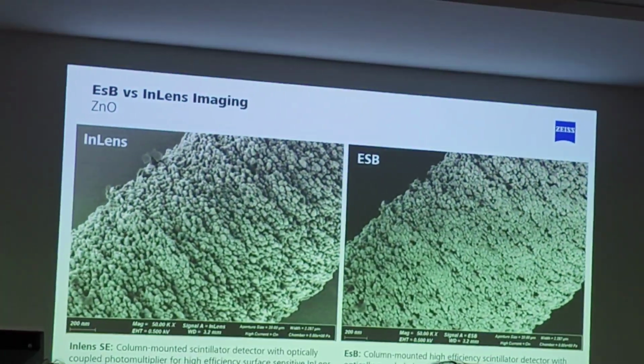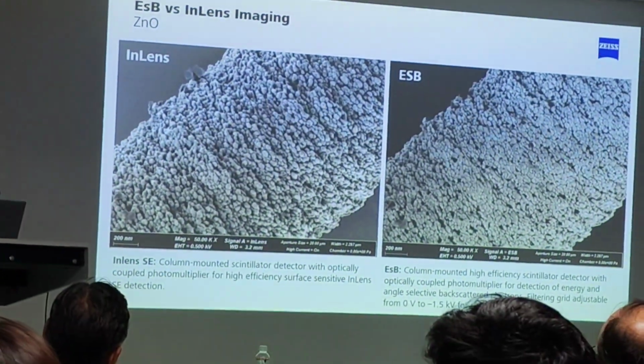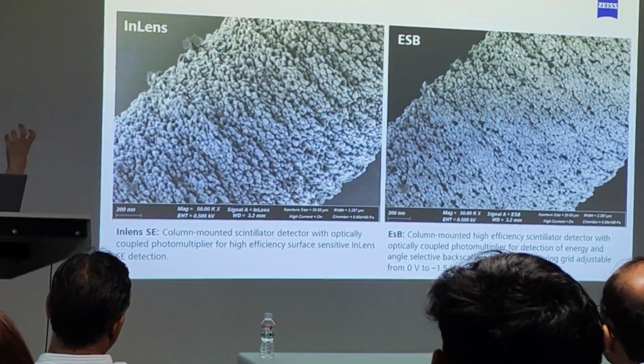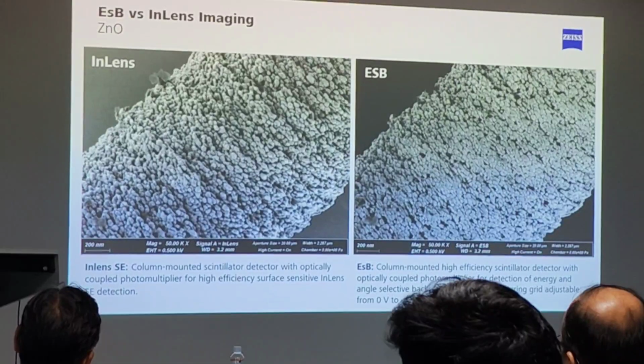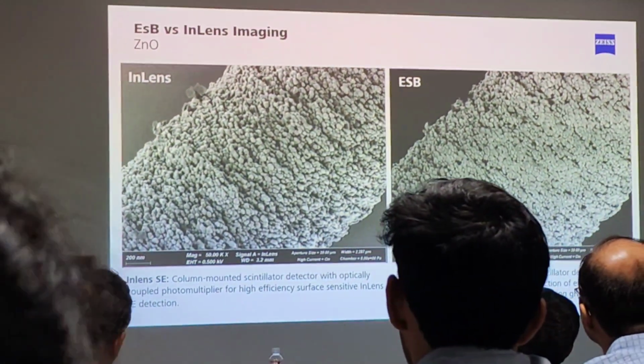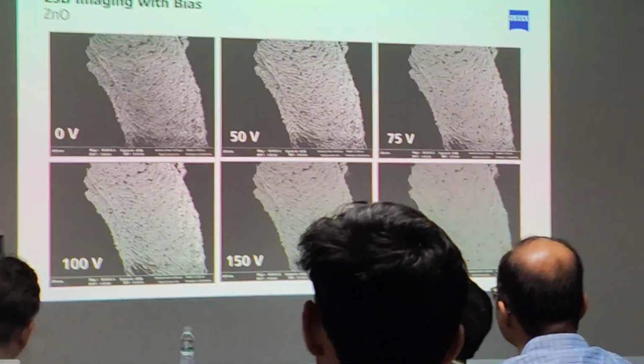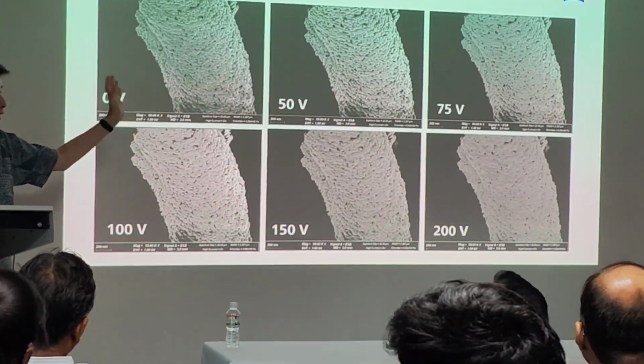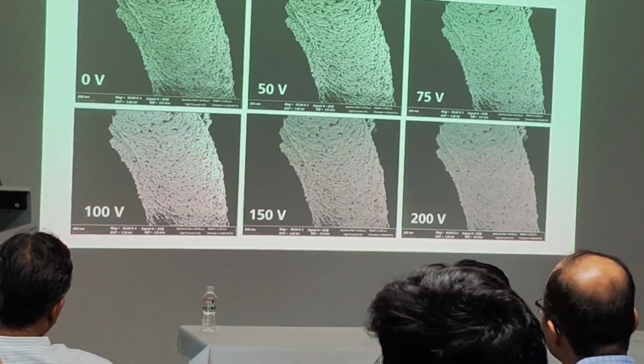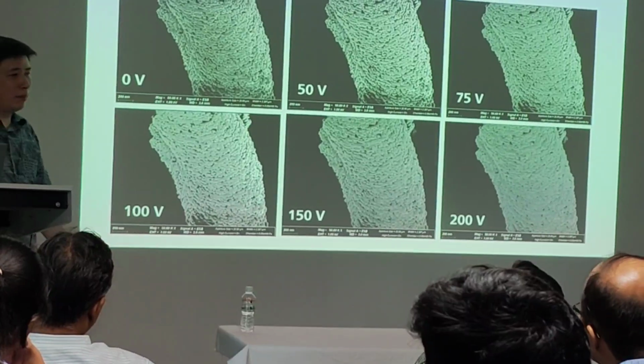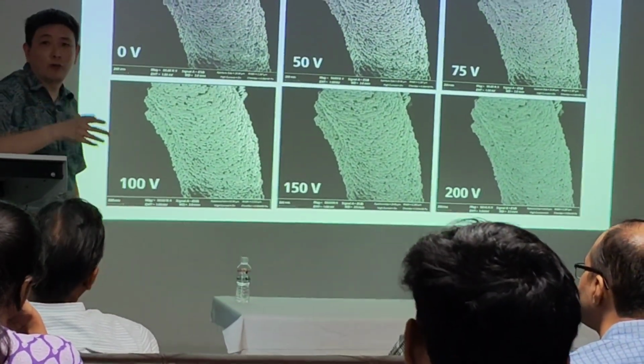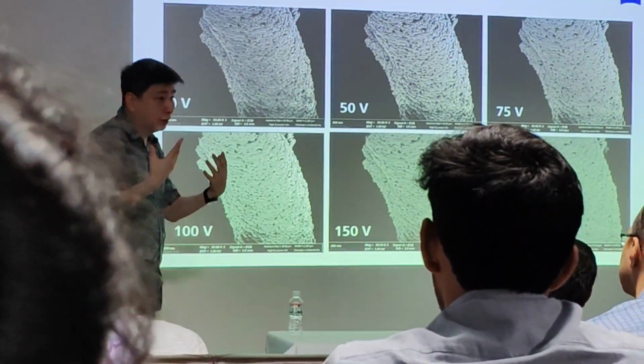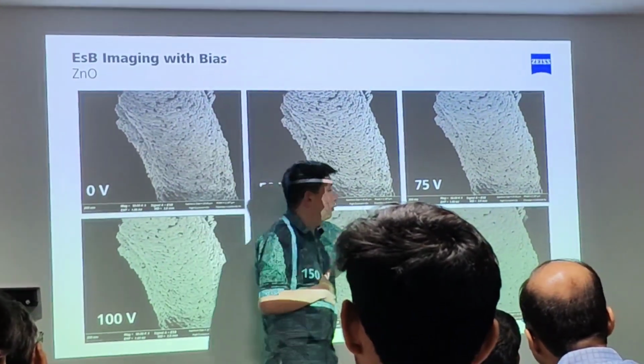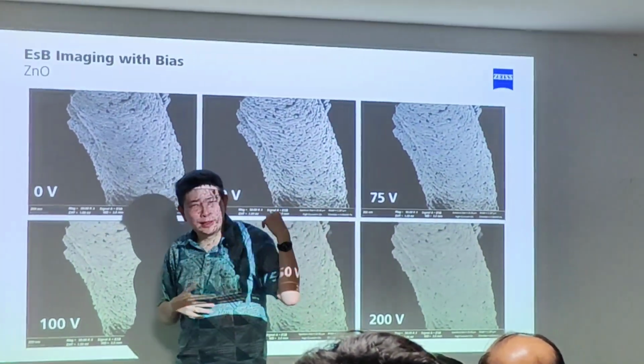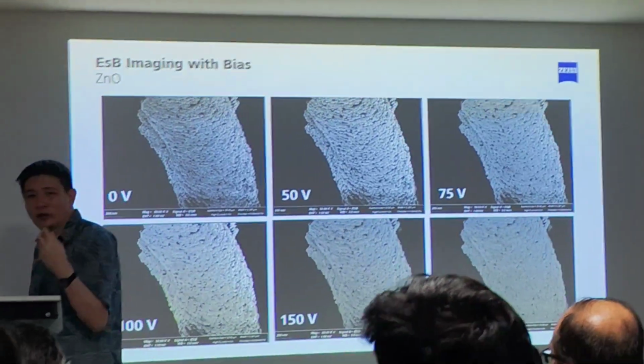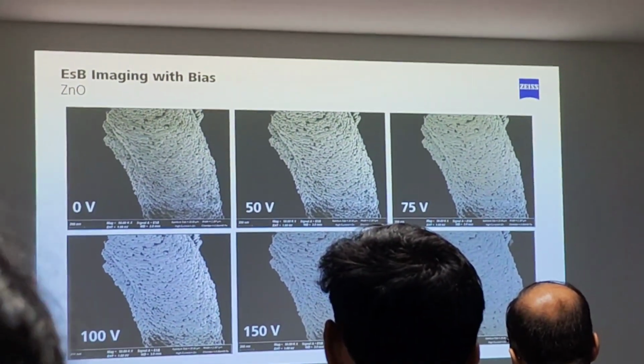This is a zinc oxide material, InLens and ESB. You will feel that InLens shows the particles more protruding compared to ESB at 0V. But even at 200V it's totally flat already. Yeah. And this one is a pure zinc oxide, but if you dope the zinc oxide with some other things, for example some rare earth materials, it will appear very nicely in this picture. But of course this is not the best sample because it is only zinc oxide, but if you have some other materials, some other metals, it will appear very nicely.